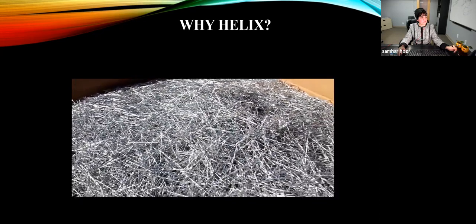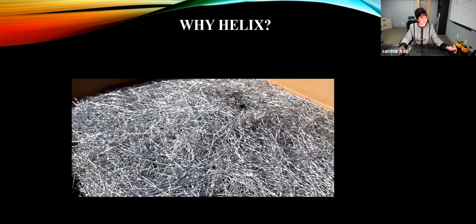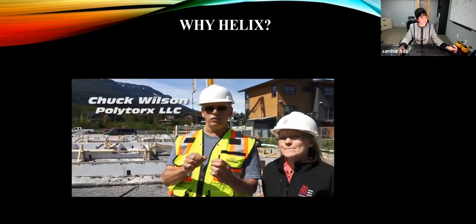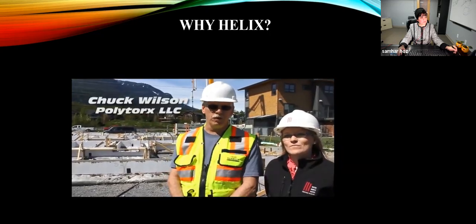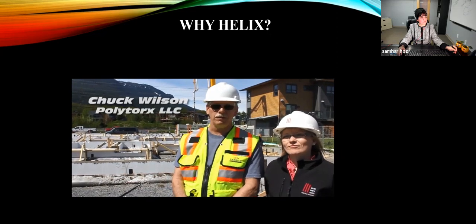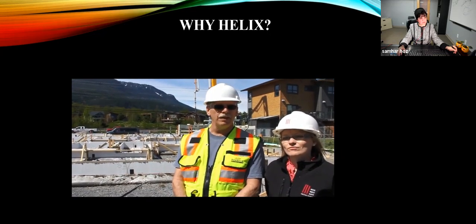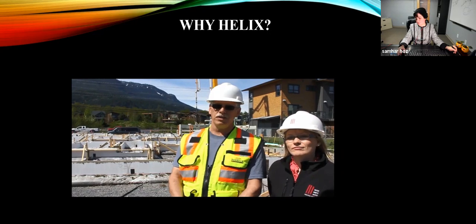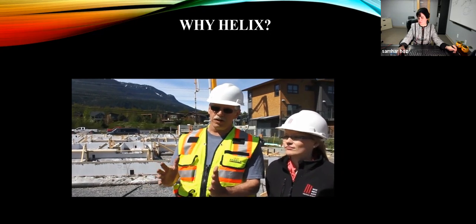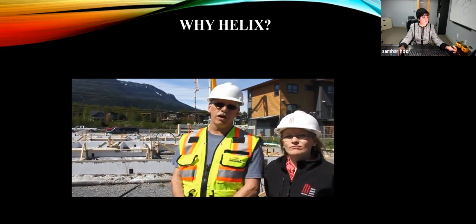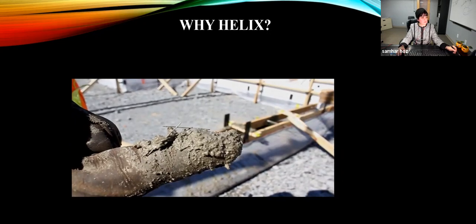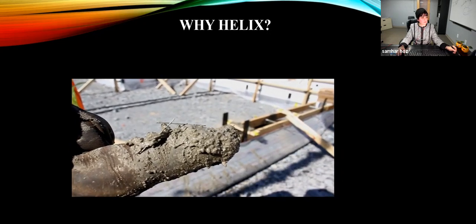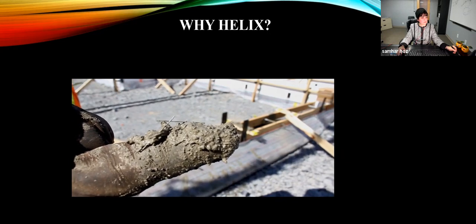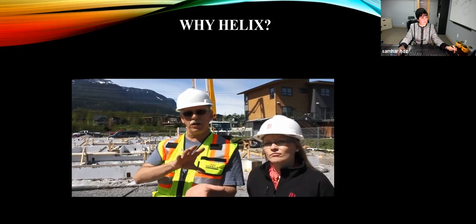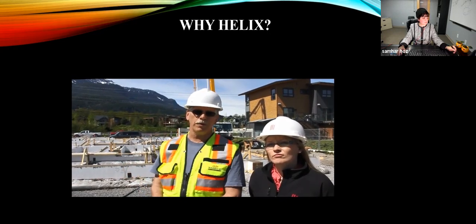Helix is actually a micro rebar. It's metal wire that's twisted, and it acts identical to rebar in concrete. It's 245 KSI steel. It's extremely strong. And the nice part about Helix is it adds reinforcement to the concrete even before the concrete wants to crack. The reason is that Helix actually makes the concrete flexible. With higher dosages of Helix, you can actually flex and bend the concrete without a dominant crack forming.